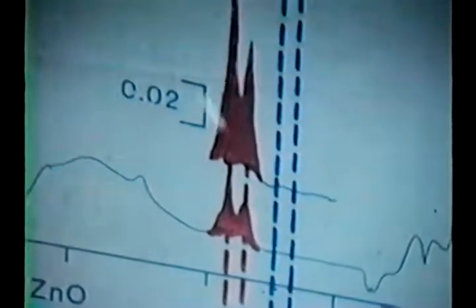We have evidence by high pressure IR spectroscopy on the copper system that formates are formed very readily between cesium hydroxide and carbon monoxide. This is nothing new in this business, but on the copper-zinc catalyst, the formate frequencies are shown here. As soon as we add these 20% of surface coverage of cesium, the formate frequencies are clearly associated with cesium only. The cesium takes over the formate chemistry on these catalysts, and nothing is present on the remaining copper-zinc oxide formate type. These are incidentally frequencies that are within a few wave numbers of reference cesium formate compounds that are known. And so what happens is that the activation of carbon monoxide is really taken over by the cesium, and that is the essential effect of the promotion of the carbon monoxide activation.